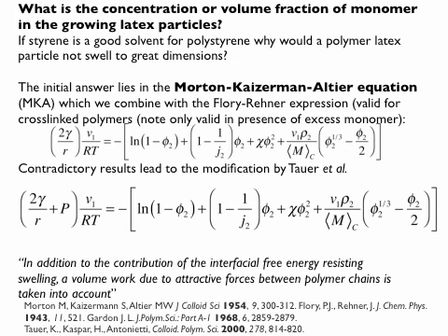You stir them up, let it come to thermodynamic equilibrium, and then you measure how much is in there. So you could, for example, separate the monomer from the swollen particles by centrifugation. And then you can measure how much monomer is in there, either by gravimetry, as in blow everything up and see how much solids you've got left, or for example, by density measurements.